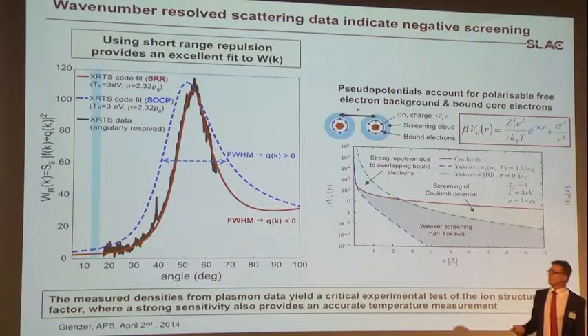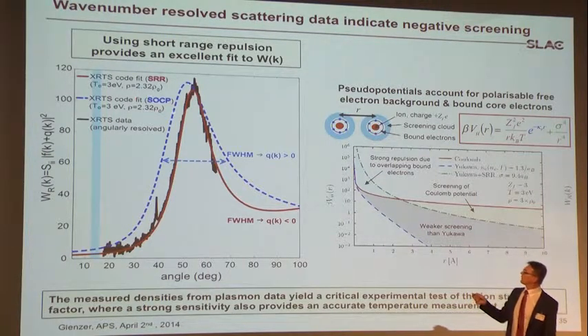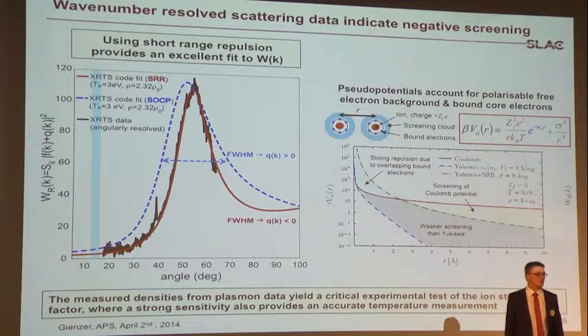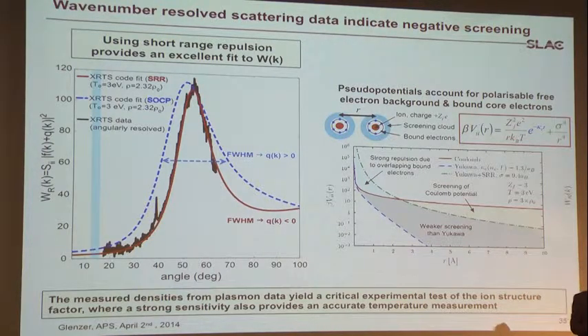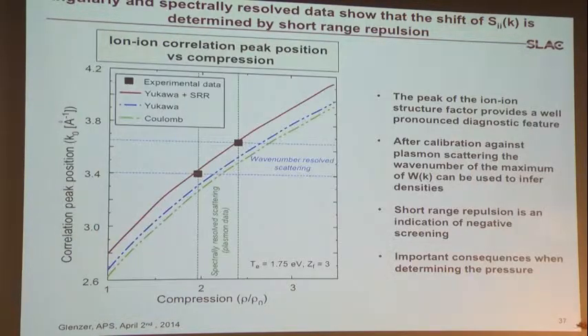Previous theories have used a screened one-component plasma, which gives you the blue dashed curve. And there's just no way that this curve can ever agree with experimental data. So now we believe we have a very good theory that describes the ionic potentials and that describes the elastic scattering amplitudes. So let's do another check. Let's look at the peak position of the ion-ion correlation peak in angle. And let's do that here.